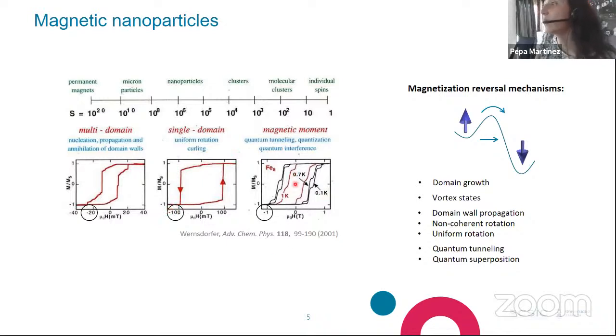And finally, when quantum effects start being an important mechanism in the reversal of the magnetization, for instance in magnetic molecules like iron 8 or the very well-known manganese 12, one finds these typical steps that are not due to the formation of domains, but to the tunneling of the magnetic moment corresponding to the different states that are quantized, okay, and this quantization becomes apparent experimentally.